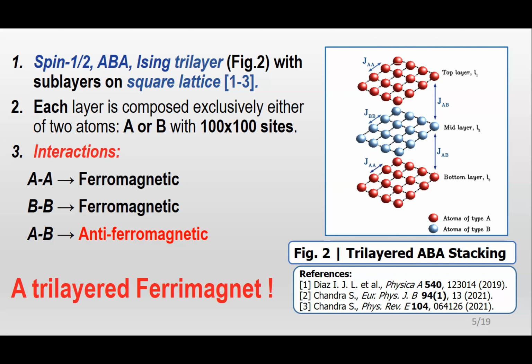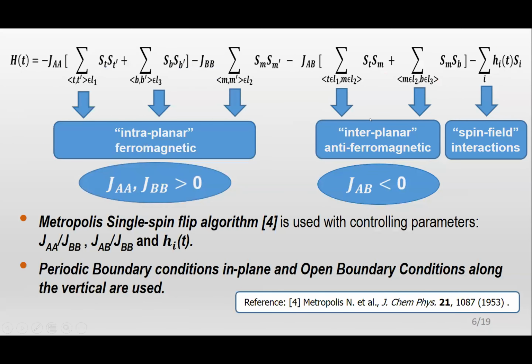In figure 2, this is a miniaturized version of the system that is used in the simulation, where in the real simulation each plane has 100 by 100 sites on a square lattice. Moving ahead, the Hamiltonian on the slide is used for simulation. First three terms are intraplanar ferromagnetic terms for the top, bottom, and the mid layers respectively, whereas the fourth and fifth terms are the interplanar antiferromagnetic terms, and the sixth term is basically the spin field interaction term.